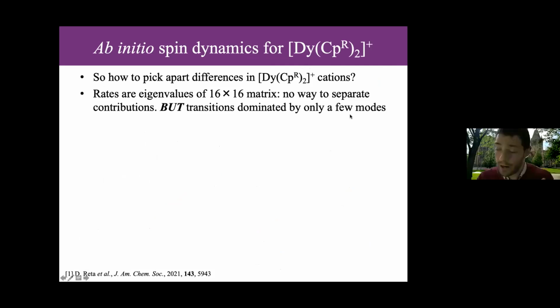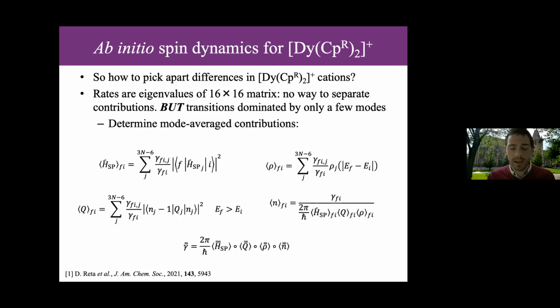So actually on average, it's only about anywhere between say 2 and 3 at most. Often it's just 1 that dominates. And so for each transition, you can actually simplify this matrix quite a lot. And so what we decided to do was think about the mode-averaged contributions to the relaxation matrix.